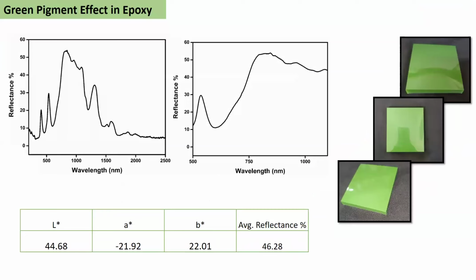So this was one thing you should understand, that any polymer, whether it is polyimide or PVDF or epoxy or polyester or polyurethane, all these polymers which are currently used for paint application, whether the polyacrylic emulsion or polyurethane emulsion. Today, we all work for emulsion paints, and none of these polymers have IR reflectance property. They have only less than 10% IR reflectance property, and this project also came to us. So we started introducing this IR reflective pigment modified by rare earth. We thought of putting it in epoxy, and we also found that the epoxy composite is having an excellent IR reflectivity because of these multifunctional colorants.